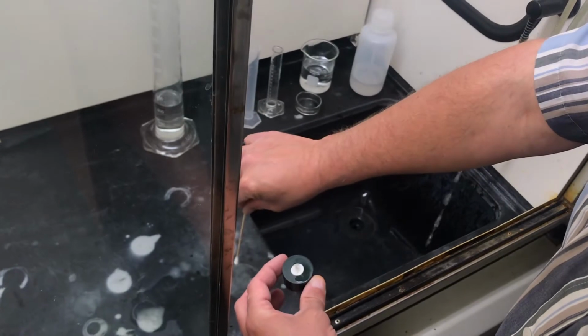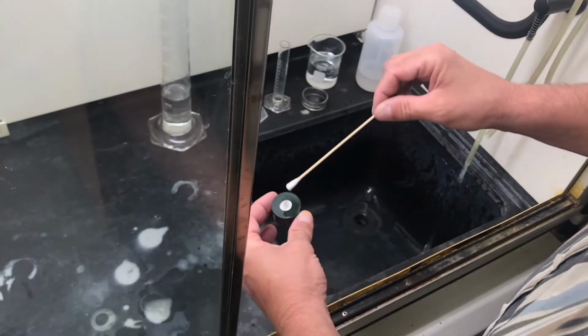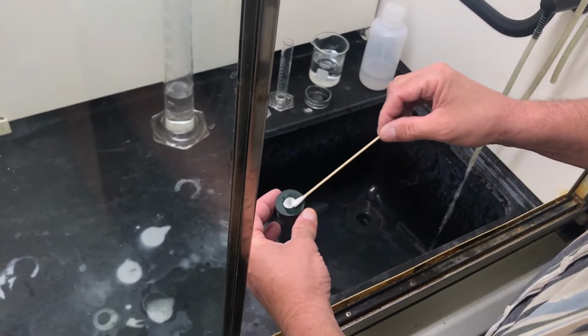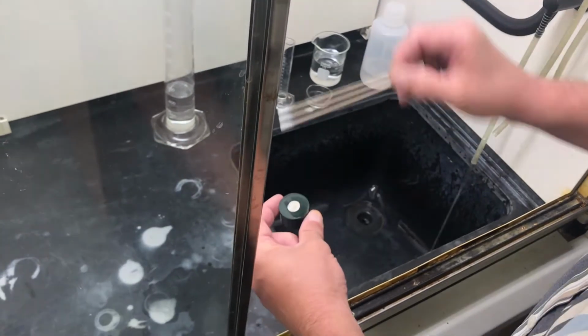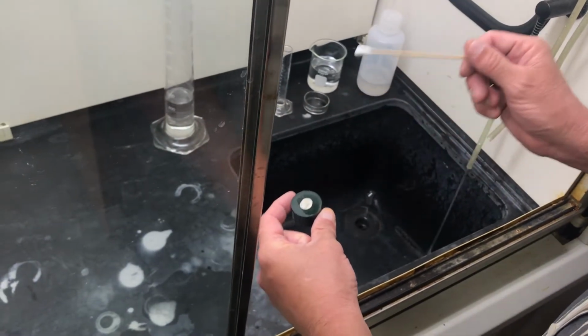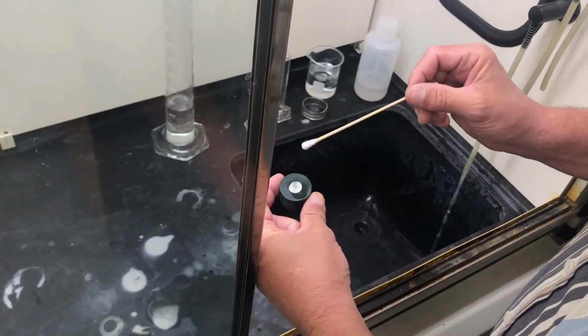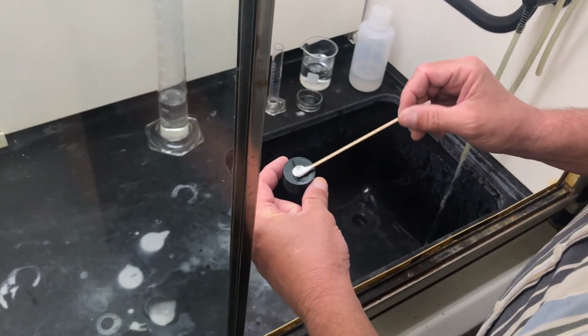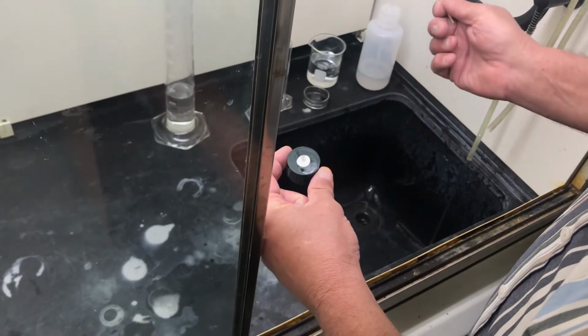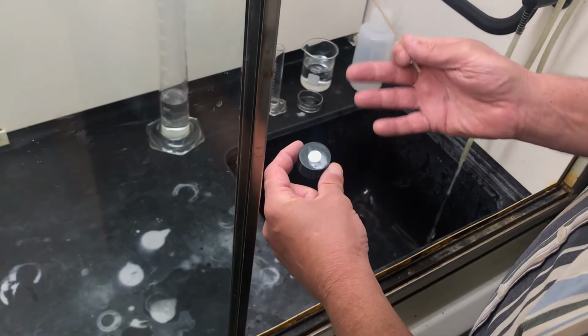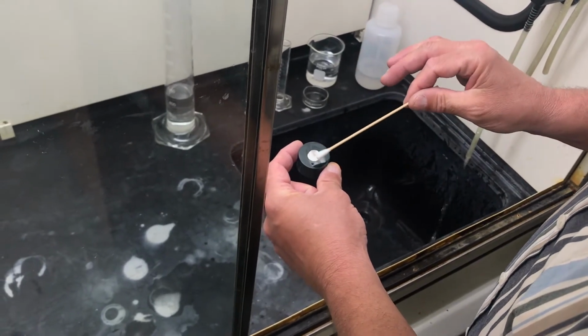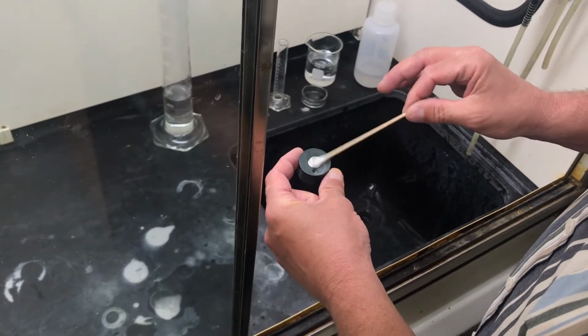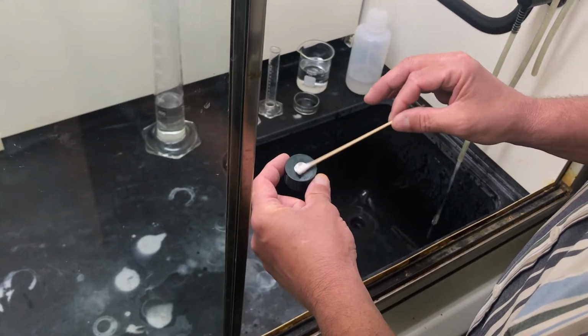Again, you will dip your swab in the acid, gently swab the surface of your sample. Don't press hard, just gently swab multiple times. Keep going back and forth. The reason is, if you put the acid on there and let it sit, it will oxidize and build up what we call smut. You don't want to do that. So you want to keep a gentle wiping action as the etchant is working.